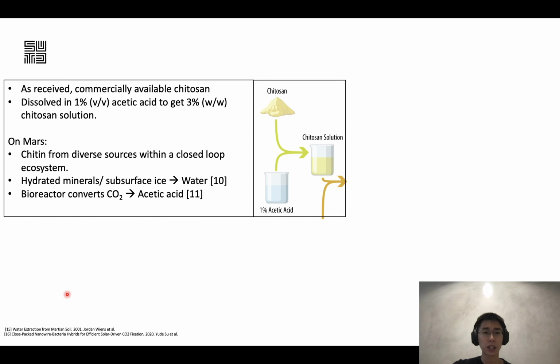First off, for chitosan, commercially available chitosan is bought off the shelf, and we dissolve it in dilute acetic acid, about 1% in concentration, to get a final 3% chitosan solution. This 3% chitosan solution is then mixed with Martian regolith. As I mentioned before, chitin can be derived from different sources inside a closed system.